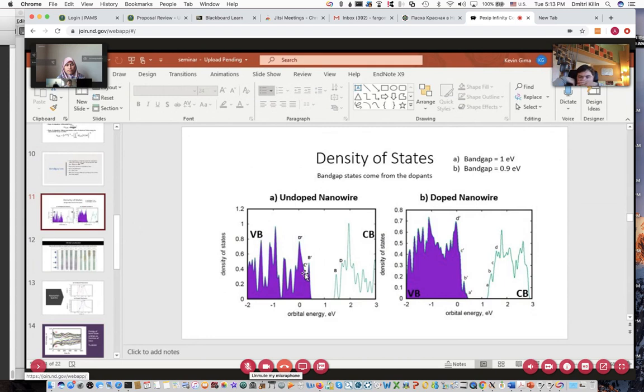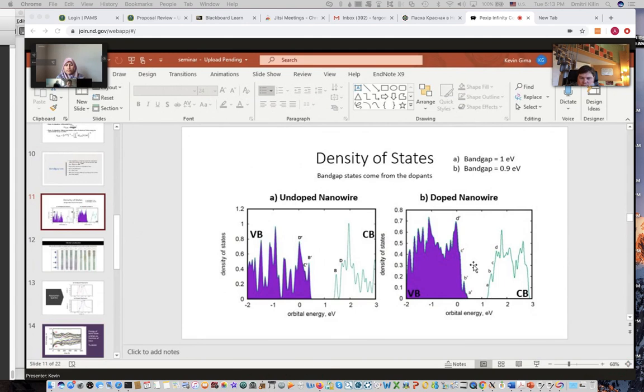Okay. So the next slide here is my density of states for panel A, my undoped nanowire, and panel B, my doped nanowire. In panel A, my band gap is 1 electron volt. In panel B, my band gap is 0.9 electron volt. So two quick things to point out here: by doping, we have states A prime and A in the valence band and conduction band respectively, and then we have another state, C, in the conduction band here that we didn't have in the undoped nanowire. So doping has introduced three new states near the band gap.